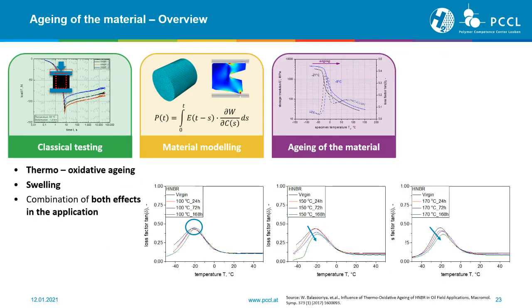Good. Now, when we're leaving the material models, we're going in the direction of aging of the material. And aging of the material, when we think back to different applications, no matter if oil and gas, space, or some industry applications, we always have some media, some temperature, some harsh environments, which directly reduce or impact the lifetime of our materials. And here, when we apply higher temperatures, we are talking about thermo-oxidative aging. When we have some oil or swelling agents, then the material will swell. And for sure, when we have both, media and temperature, we have a combination of both effects, which leads to a higher impact of thermo-oxidative aging or swelling.